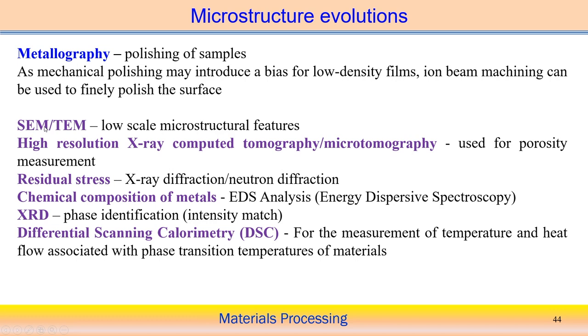For example, SEM (scanning electron microscope) and TEM (transmission electron microscope) are used for low-scale microstructural features. If you want to observe dislocations — a type of crystal defect — dislocation observation is not possible using the optical microscope. In those cases, we should go for transmission electron microscopy to visualize dislocation density. Sample preparation is also required for this — we usually follow ion beam machining. Very good surface preparation is required to observe dislocations using the transmission electron microscope.